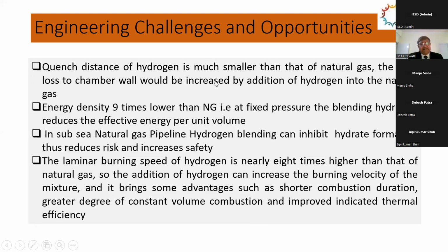And one advantage in the case of a submarine line, of course, we are talking of only the natural city gas distribution pipeline, but in the case of a subsea pipeline, natural gas hydrogen blending can avoid hydrate formation. Hydrate formation in any natural gas pipeline is a major risk, so it reduces the risk. And the laminar burning speed of hydrogen is nearly 8 times higher than that of natural gas. So addition of hydrogen can increase the burning velocity and brings the advantage of shorter combustion duration and constant volume combustion duration. You get improved thermal efficiency of the engine. Next slide, ma'am.